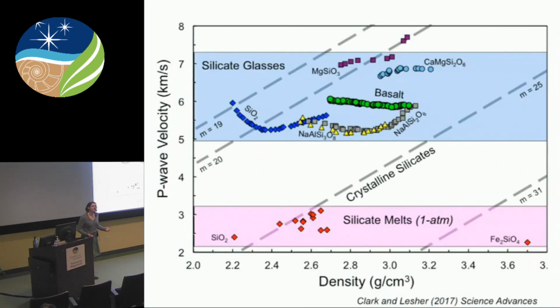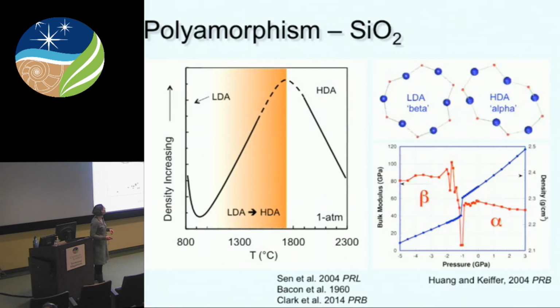And what's really interesting is that when we look at the effect of pressure on silicate glasses, what you can see is that as you increase density by increasing pressure, you have this very weak pressure dependence. Some are weakly positive pressure dependent. Things like basalt actually have a negative pressure dependence for velocity as you increase pressure. So this weak pressure or density dependence is similar to what we see in silicate melts at 1 atmosphere and is in direct contrast to what we would predict for crystalline silicates.